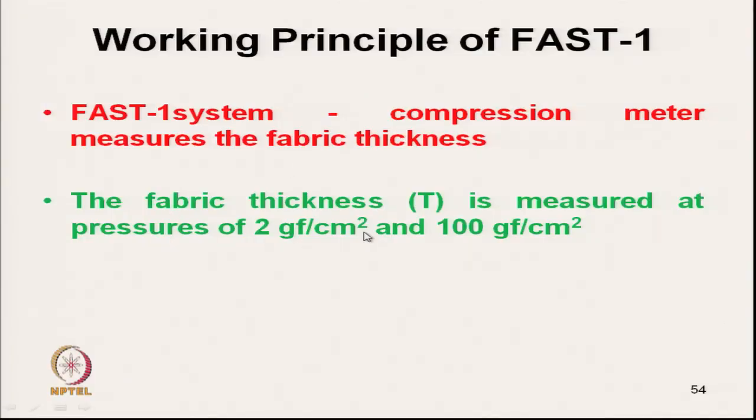The fabric thickness T is measured by a pressure foot at a pressure of 2 gram force per square centimeter as well as 100 gram force per square centimeter.